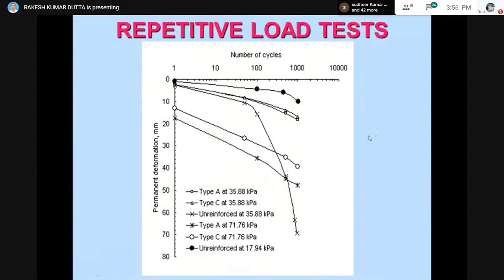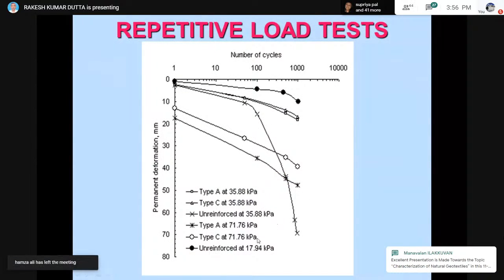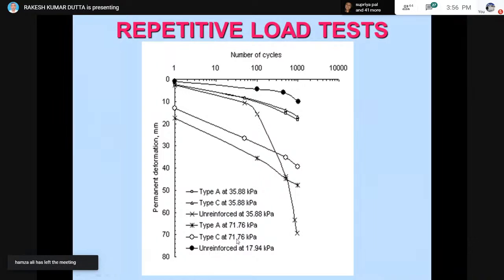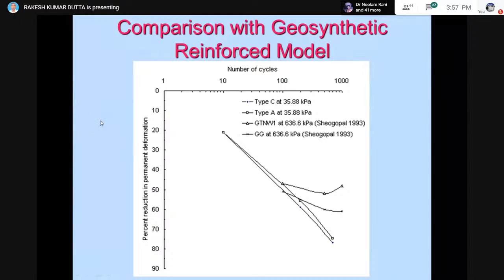Now this is a repetitive load test. Repetitive load tests were conducted and compared with the earlier study reported by Sheogopal, where polymeric geosynthetics were used. Here you see type A and type C at different repetitive loadings. As we increase the load, the permanent deformation is lesser with the introduction of the coir geotextile at the interface of these two layers. This is the main conclusion we drew from the repetitive load test reported in 2002. Again, this is a comparison of percentage reduction in the permanent deformation in the study conducted in 2002 and the earlier one.